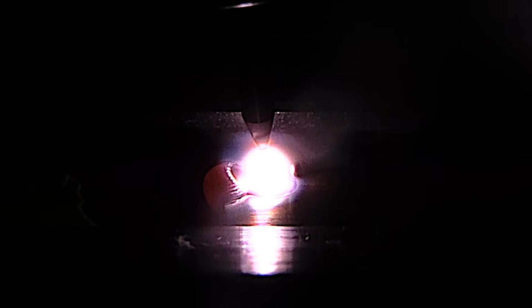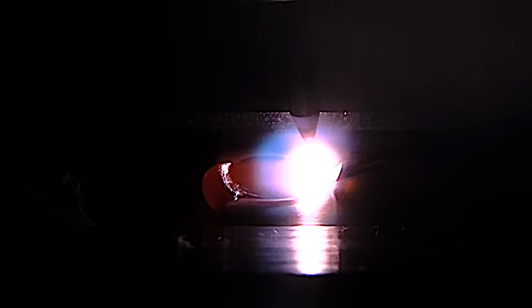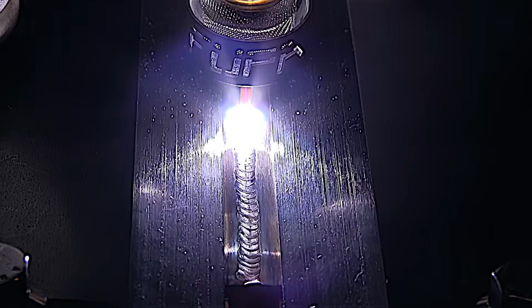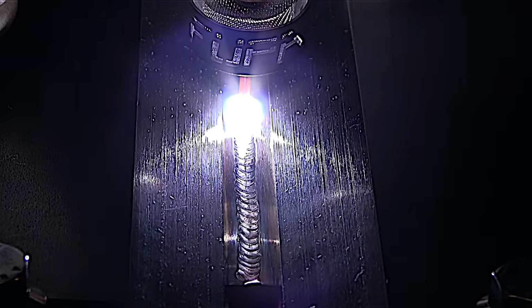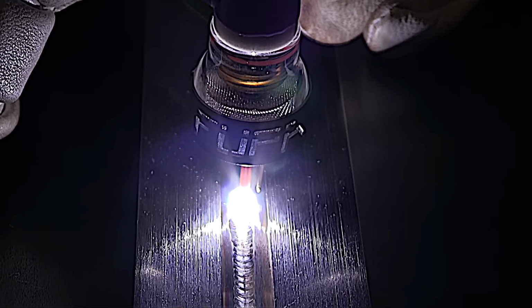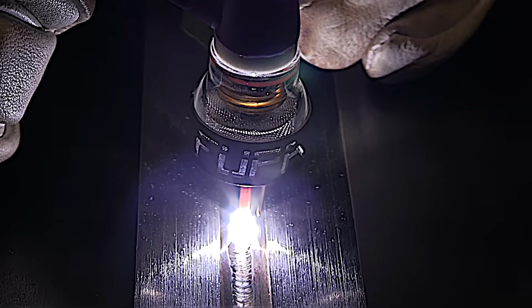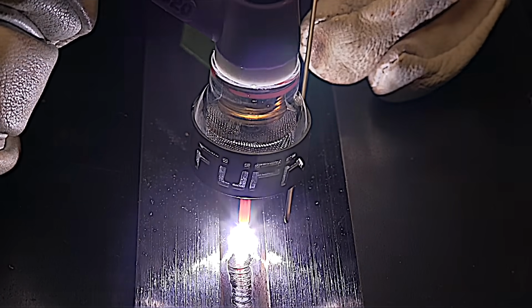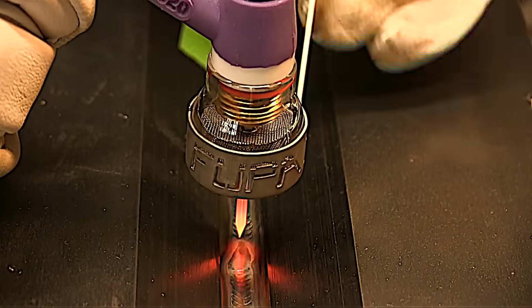We're going to use a similar technique to weld from an edge where there's a tack on the end. And what you want to do is watch the back of that puddle and give it just enough amperage that the back of that puddle washes about halfway through, and then move on. You don't want to curl that end away and blow it away. On an aerospace test, there are some provisions for screwing up an end, but you don't want to. Why not just make the end good? Put your best foot forward.